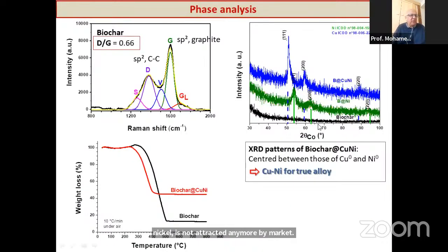For example, by XRD, we show that the nickel or copper are in the metallic state, with the existence of some oxides at the surface of the nanoparticles, and the graphitization degree of the biochar is monitored by Raman spectroscopy. We determine the D to G peak ratio, and usually we check whether the G band has an increased intensity, height, or peak area, dependent on the condition of the pyrolysis. And of course, TGA permits to monitor the loading of the nanocatalyst on the biochar.